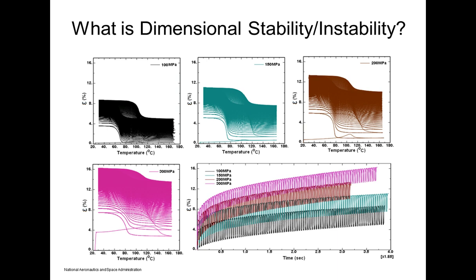Okay. The next question is, has the actuator system been researched for flow controls? We have done a number of applications where we've looked at flow control type devices or valves. The limiting issue with shape memory really comes down to what bandwidth you need, because the only thing that governs the transformation in these systems is a heat transfer problem, getting the heat in and out of the component. And so if you need a bandwidth that's higher than what you can do in your heat transfer problem, they won't work for your application. But outside of solving the heat transfer problem, being able to get the heat in and out of the component fast enough for your application, these materials have been looked at for all kinds of things, including flow control devices.